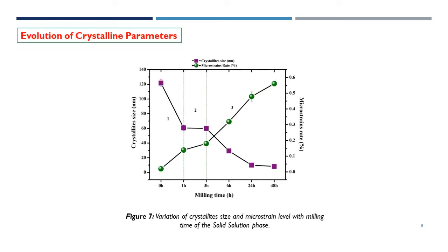Figure 7 depicts the average crystallite size and the microstrain rate of samples. The unmilled iron cobalt nickel mixture had a crystallite size of around 121 nanometers. A notable sharp decrease to 60 nanometers after 1 hour of milling is shown, which is primarily due to the formation of a new solid solution. Between 1 and 3 hours of milling, there is almost no change in the crystallite size.